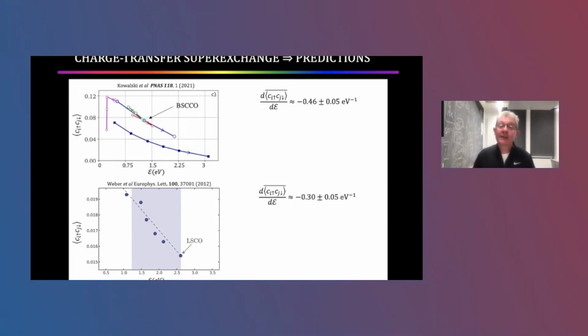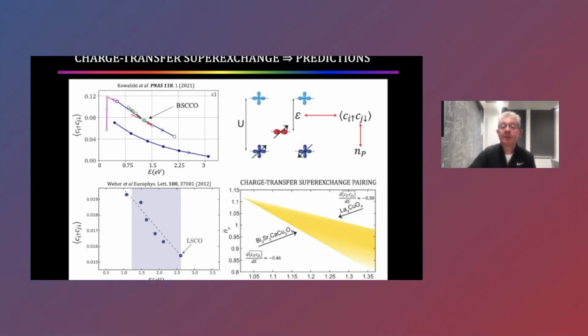Now, unfortunately, you can't measure Ci dagger Cj. It's a complex field. In our universe, you have to measure a real number. So what experimentalists can measure is the magnitude squared of the pair wave function amplitude, which is the number density of the pairs. So for BISCO, the Sherbrooke prediction is that the rate of change of condensed pair density with charge transfer energy should be 0.46 per electron volt if charge transfer superexchange is the mechanism of high-Tc.